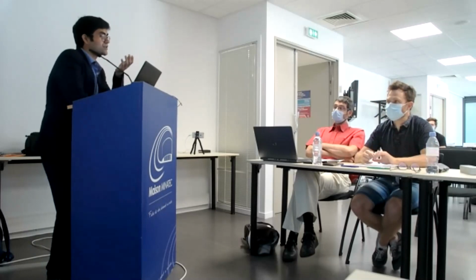And is there a way to identify this by making some solute profiles close to grain boundaries? Yeah, we can imagine doing simple experiments, making simple solute profiles close to the grain boundaries, to see which elements are moving into the solid and which elements are particularly localized along the grain boundaries. Based on that, we can probably understand which elements tend to back diffuse and which elements tend to stay in the liquid.